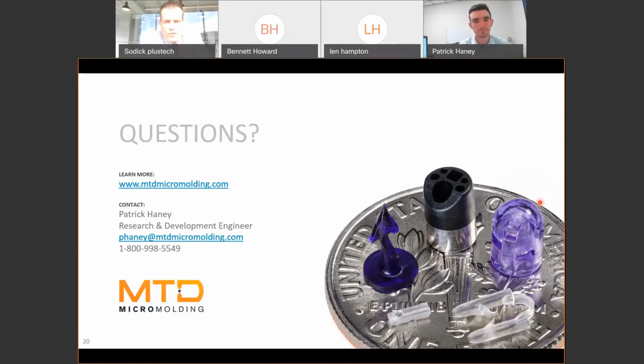Wonderful. Have you used or evaluated the intrinsic viscosity and its relationship to the viscosities you are seeing? Yeah, actually, we measure intrinsic viscosity in-house. That's something that we use for incoming material as well as release criteria to our customers, on a regular basis. Something that we see is we usually see some IV loss, right? Because IV ultimately is a derivative of molecular weight, right? So we end up seeing some IV loss, but it's manageable because our systems are specialized to what we do. It's very marginal, and it's something that we can actually predict, right? We have enough experience with most of the polymers that we run here where we'll see minimal loss that we can see coming down the road. So it's something that we can anticipate and prepare for.